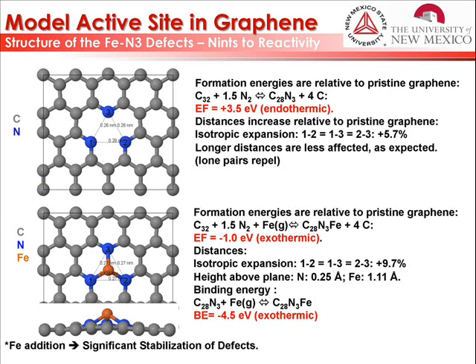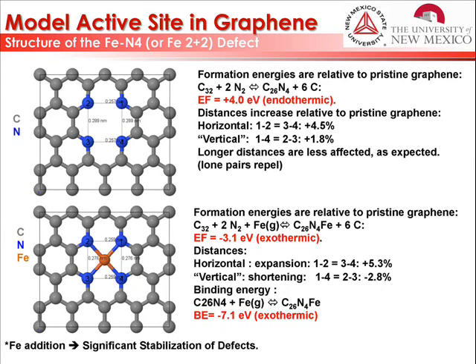This site is more difficult to make. Originally, everybody thinks about this site because it's similar to a porphyrin. But this site energetically has 2 vacancies and 4 substitutions. The other site has 1 vacancy and 3 substitutions, which is less. And voila, something that was not published but is currently being observed.